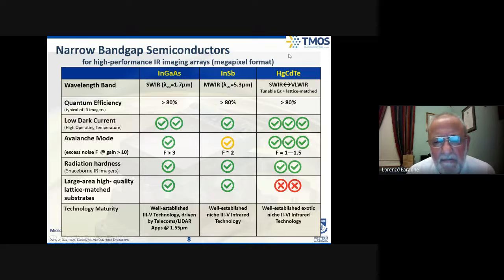Now, what this table shows you is pretty much the dominant semiconductor technologies in those different wavelength bands, for various reasons. In the end, remember that you have to absorb photons, and so you really want a bulk semiconductor. Indium gallium arsenide, in the shortwave infrared up to about 1.7 microns, is a magnificent infrared detector material, up to 1.7 microns.